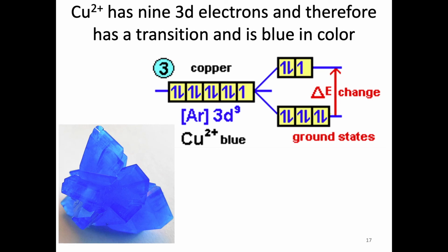All right, so now let's look at copper. So copper 2+ in particular. Again, if you got the same thing I did, you should get argon plus 3d9. So we're almost completely filled here with the d electrons, but we have one spot left. So one spot left means that there's still room for transition, right? So we can still promote one of these electrons to the higher energy state. In this case, the x squared minus y squared or the z squared, and then it could go back and create light. And so in this case, with copper 2+, these compounds tend to be blue